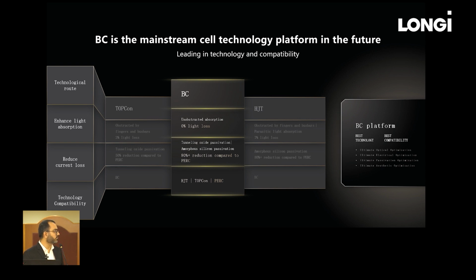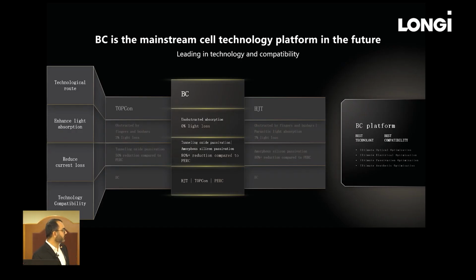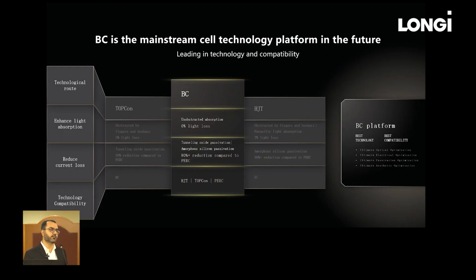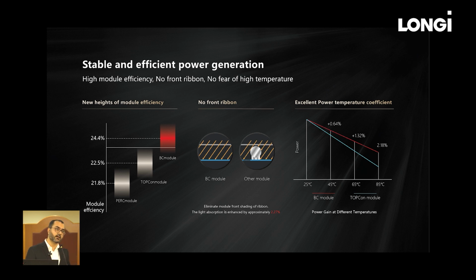But with back contact, you can integrate whether it's TOPCon, HJT, or PERC, and achieve 0% light loss and move forward with it. With PERC modules, if you remember, the maximum module efficiency you would get was 21.5 to 22%. With TOPCon, currently even with Hi-MO 7, you are seeing 23.2 to 23.3%. But when we introduced Hi-MO 9, the module efficiency rose up to 24.4%. So we took a big leap of about 1% in module efficiency.